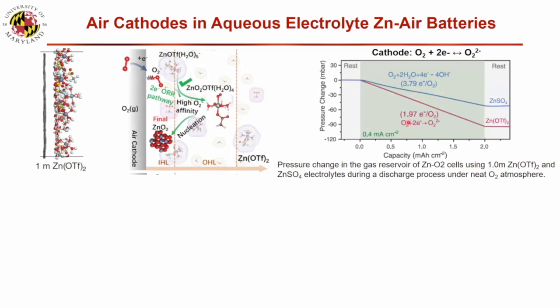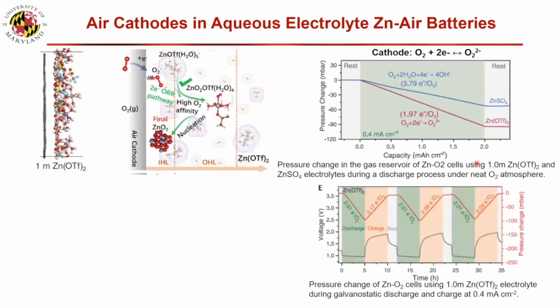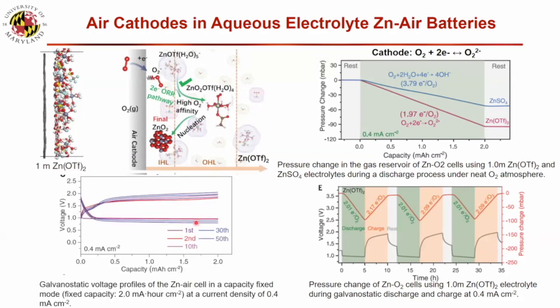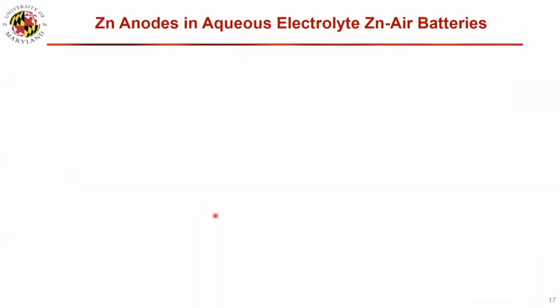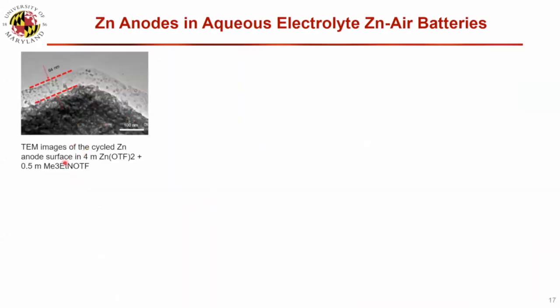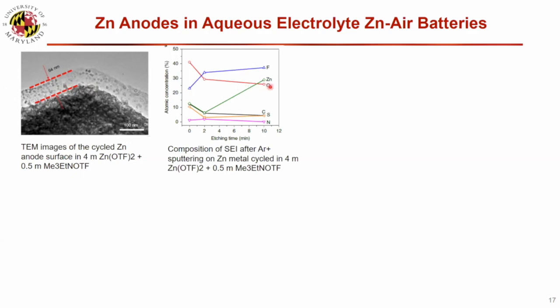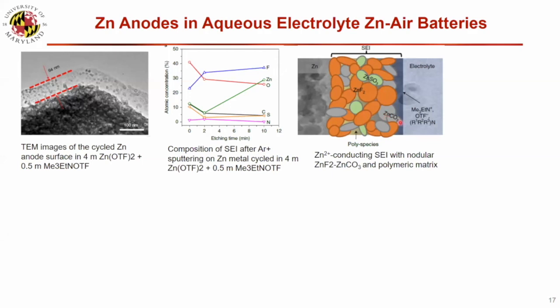We demonstrate there is a two electron reaction in a zinc OTF. And during charge discharge, they keep it reversible because the two electron reaction is much faster than four electrons. So they keep the cycle life really stable and very fast charge. And also, when we put Me3EtNOTf, Me3EtN can reduce to form the SEI, the zinc fluoride SEI on the zinc, they can block the zinc dendrite. When we check the SEI on the zinc surface, you have really high fluorine and also oxygen. And then we think they have zinc fluoride, zinc carbonate on the zinc surface.